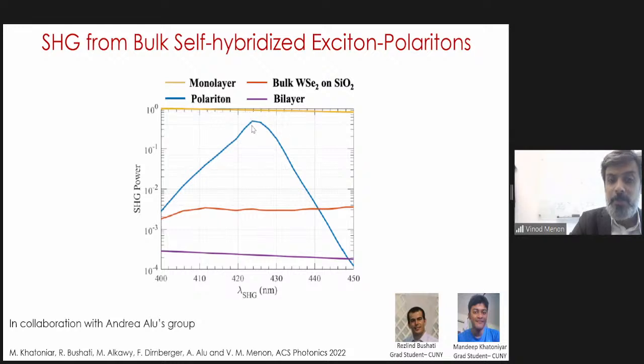But the moment you go into the Polariton system, you suddenly boost up by 2 orders of magnitude this nonlinear response. Of course, it's a resonant phenomenon. It only happens where there is a Polariton system. And so this shows that the theory at least is able to reproduce the experimental result. So again, work led by my graduate student Rezlind and my other graduate student Mandeep.